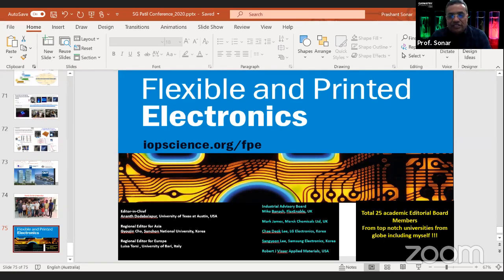The stability of materials really depends on the energy level. Most of the polymers, the ones I showed in the scientific report where we got 10.5 mobility, are very stable devices. Even when we kept those transistor devices for 2 to 3 months, the mobility values were still reproducible. For solar cells also, it is possible to get very good stability.